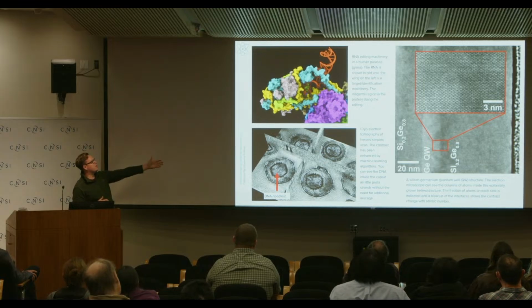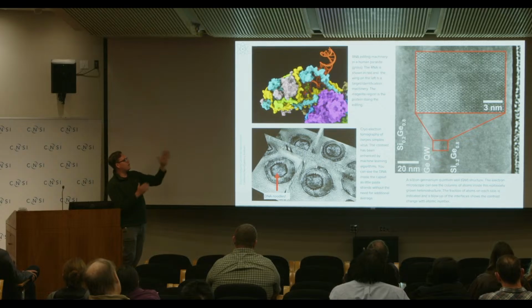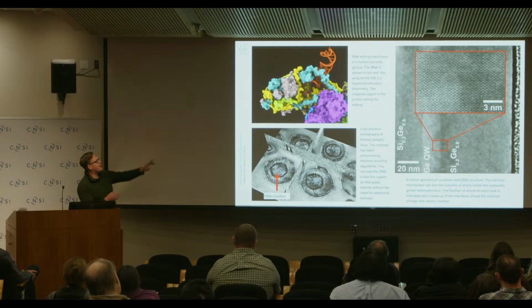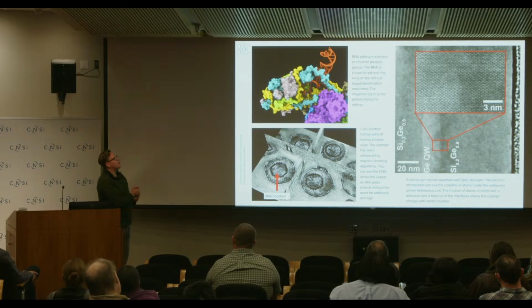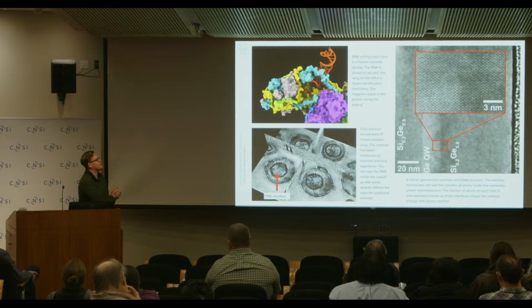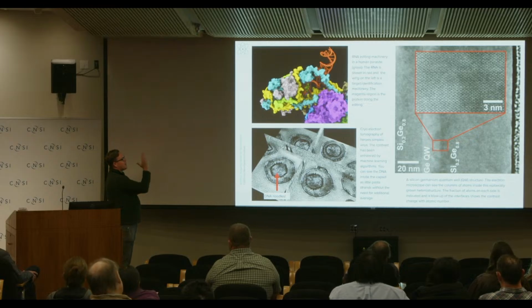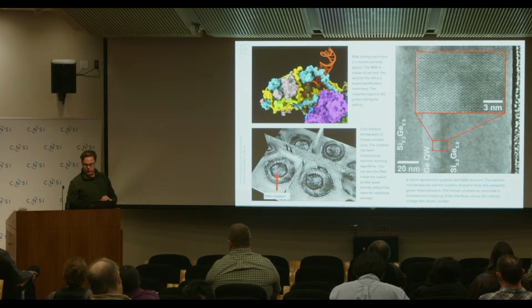So you can see the difference between the germanium quantum well layer and the 2 semiconductor layers on either end of that. You can actually see the interface nearly at atomic resolution. This particular image here is more limited by the sample than it is by the actual imaging conditions, but you can actually see that atomically sharp interface from the epitaxially grown layers really quite well.